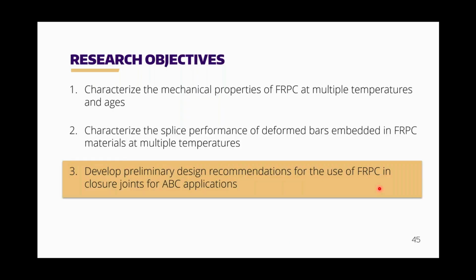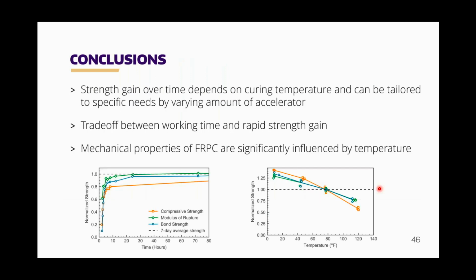And so now, to summarize everything, we're going to go through the design recommendations here. In conclusion, the strength gain over time of polymer concretes and the fiber reinforced polymer concrete depends on curing temperature and can be tailored to specific needs by varying the amount of accelerator. In our case, we use 3%. The manufacturer recommends 8.3%, and that would be for a field application where you're not trying to fuss with all these specimens.